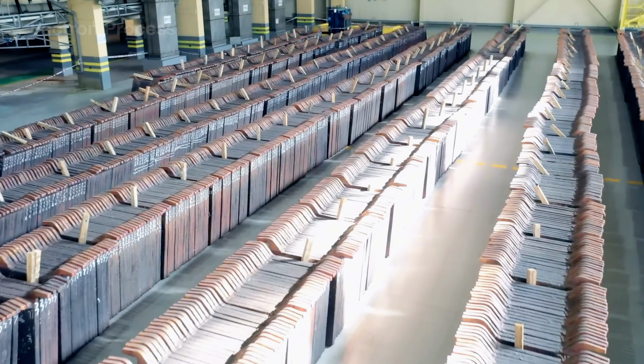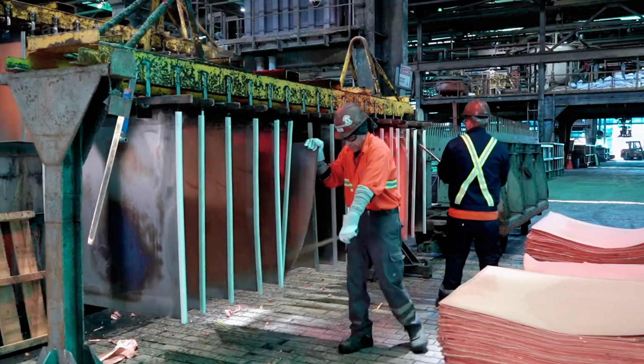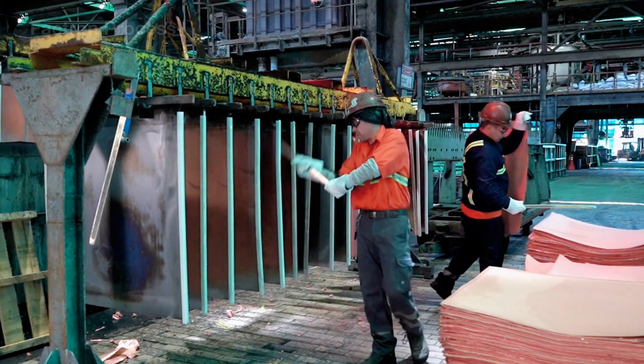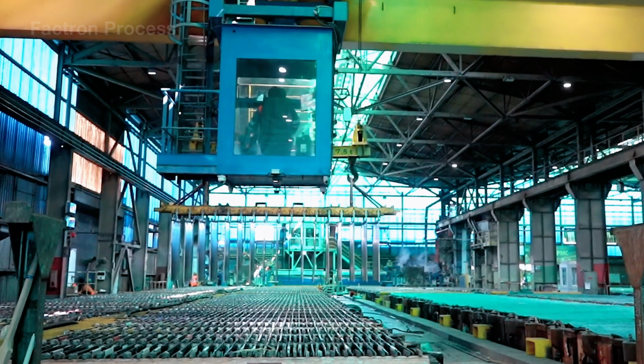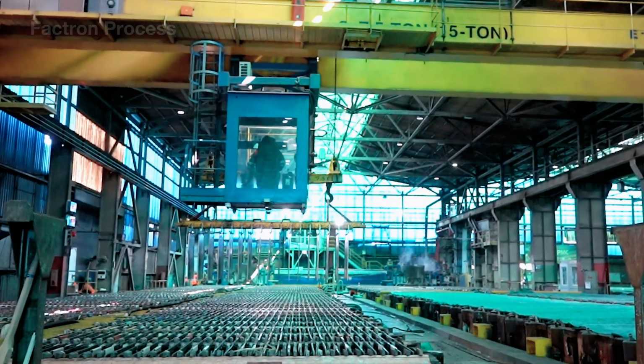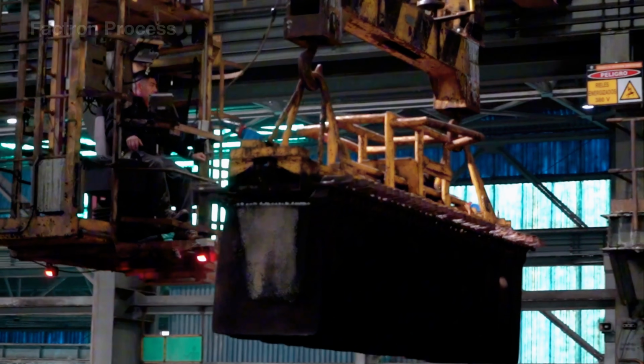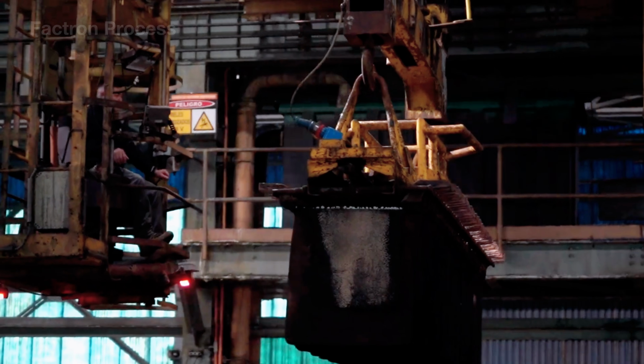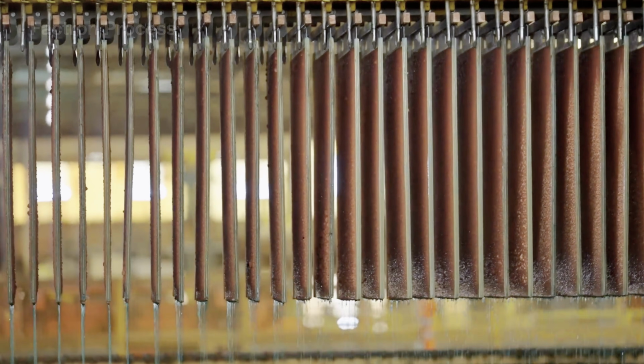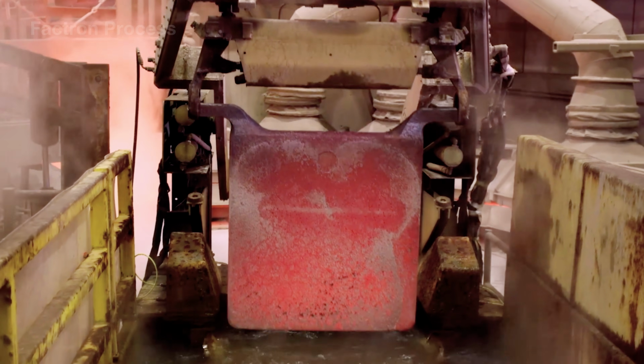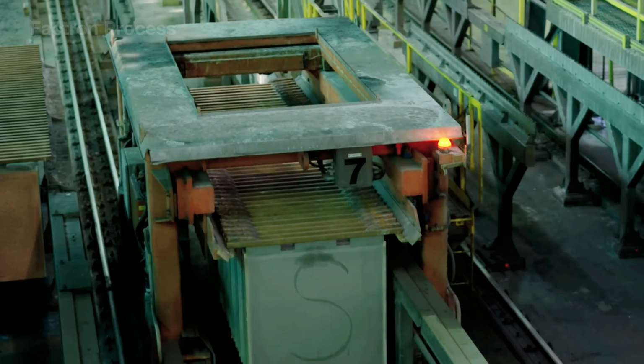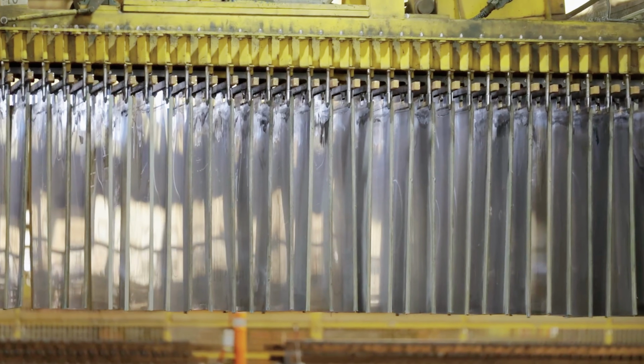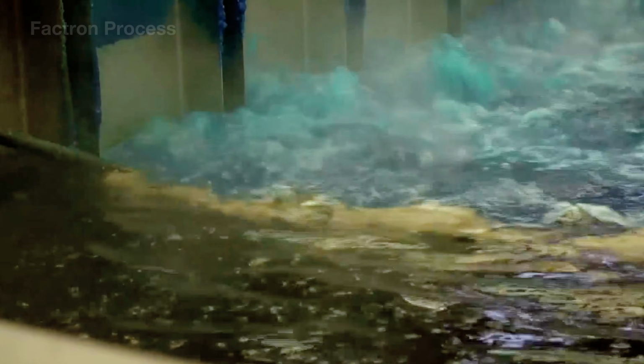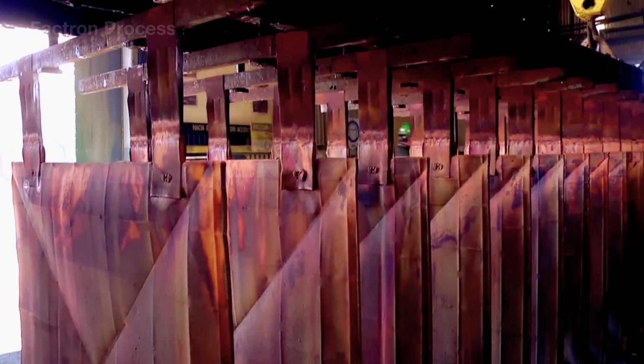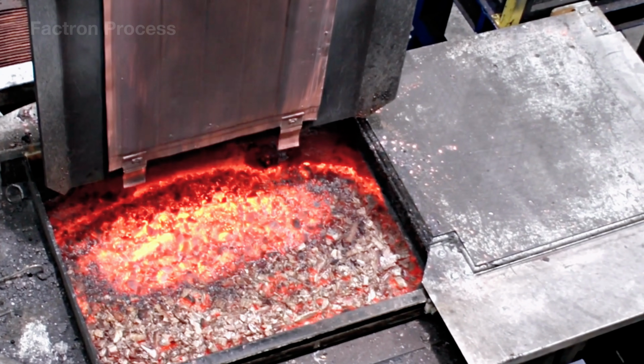Each day, the new copper layer grows thicker, while most impurities do not follow the copper and instead settle at the bottom of the tanks for separate recovery. Once the required thickness has been reached, the new copper sheets are lifted from the tanks, washed, inspected, and transferred to the forming stage. At this point, the copper has reached a purity of up to 99.99%, making it suitable for use in the production of electrical cables, motors, transformers, and thousands of other electrical devices.